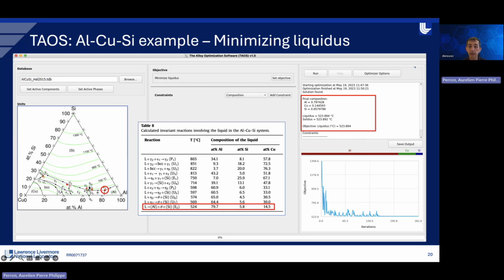So now to highlight another feature of the software, maybe in a world where you could not use a lot of aluminum, let's say because, I don't know, the powder is too reactive or it has all of a sudden become too expensive. And for your problem, maybe you cannot use more than 25 atomic percent of aluminum. So technically you cannot use the compositions that are in this shaded area. You are limited to this area. So how can you now minimize the liquidus in that composition space?